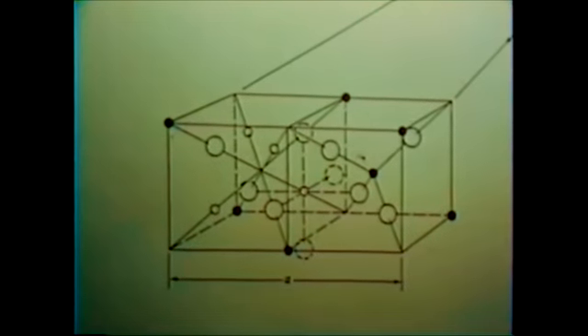Now to go to the application, all these examples I'm going to list have the cubic spinel structure. I've seen a lot of work here today about this cubic spinel structure. It's an FCC network of oxygen, and you have the cation with two environments. One is called the tetrahedral, surrounded by four oxygen, and the other is called the octahedral, which is surrounded by six oxygen. In this cubic spinel, you have one A site, the tetrahedral A site, and two B sites occupied. So you have three sites for the cations, and the oxygens are on the FCC lattice.